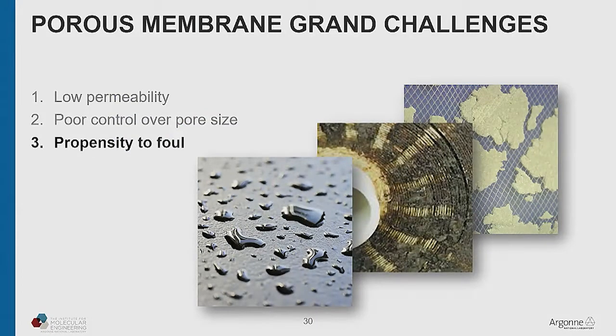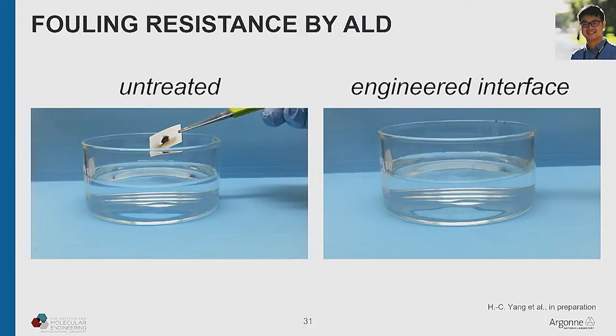So let me just show you some of the ways in which we're trying to combat these challenges. So let's start with fouling. So here's an example, and I won't go into any of the technical details. I'll just show you the result of an attempt to use atomic layer deposition to impart fouling resistance onto a commercial membrane. So this is a commercial polymer membrane, just like you would use to filter stuff that you'd buy off the shelf for next to nothing. And that is a drop of crude oil that's on the surface of that membrane. So membranes are often used in oil-water separations. They're a nice way to separate oil and water, but they tend to get very fouled by oil, which then renders them no longer useful.